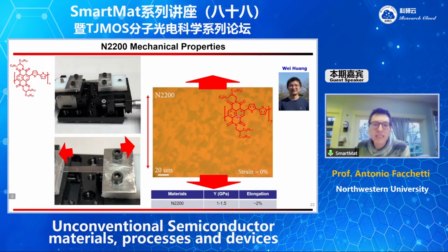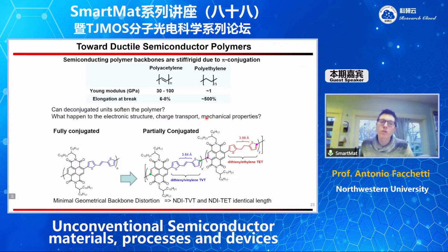So how can we plasticize it? What we did, and this is work we haven't published yet, but I want to repeat some of the concept, is to learn from comparing polyacetylene, which is a fully pi conjugated polymer, with polyethylene, which is pi deconjugated. And you see here, when you have these double bonds, the Young modulus becomes large, and the elongation at break becomes lower compared to the corresponding plastic polyethylene here.